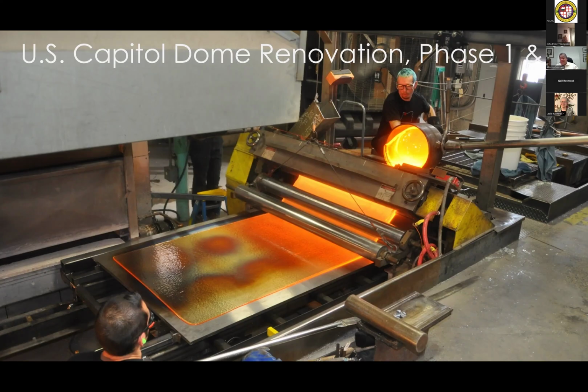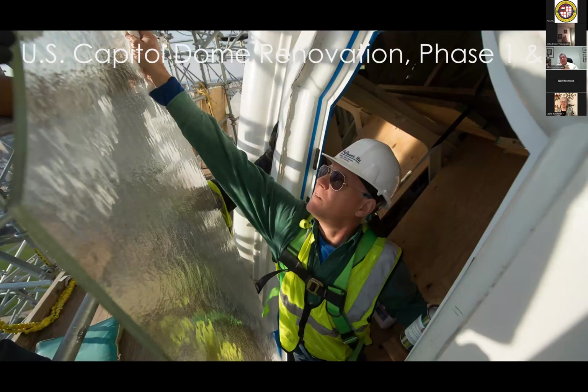But we made the glass half as thick so that we could take 2 pieces of this glass and laminate them together and create laminated glass that was as close as possible to the visual appearance of the historic glass, but is now essentially safety glass. And so that was installed over the stairway that the tourists run. They waited too long to do the project, of course, so we only installed 7 or 8 pieces of glass, and they have another 10 pieces of glass in storage waiting to be installed at some point in the future when they decide to re-scaffold the Capitol Dome.